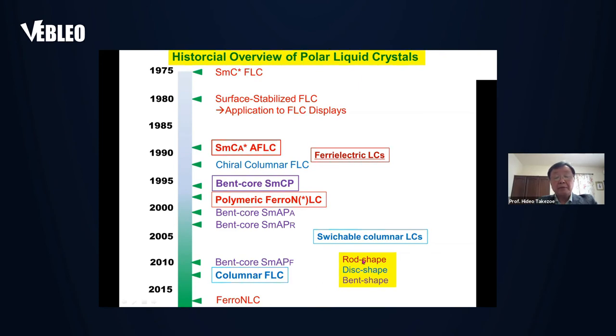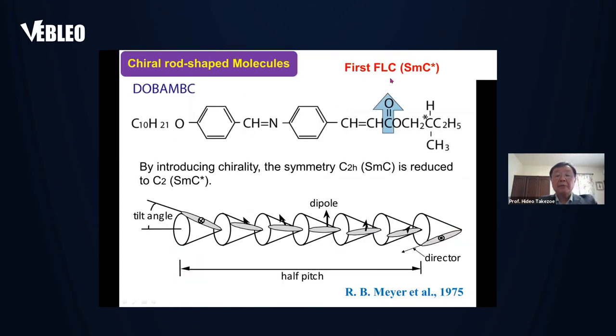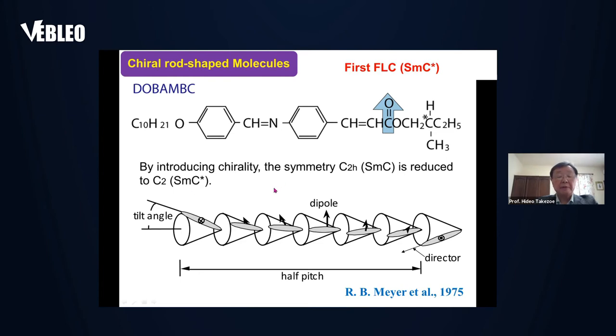These colors represent the different constituent molecules, like rod, disc, and bent. Let me start with the first ferroelectric liquid crystal, smectic C*. Based on Bob Meyer's ideas, French chemists synthesized this molecule, which has a transverse dipole and a chiral carbon. This molecule shows smectic C*; the star means chiral. So the symmetry of C2h in smectic C is reduced to C2, making it a candidate for ferroelectricity. Because of chirality, the tilt direction precesses from layer to layer to form a helical structure.